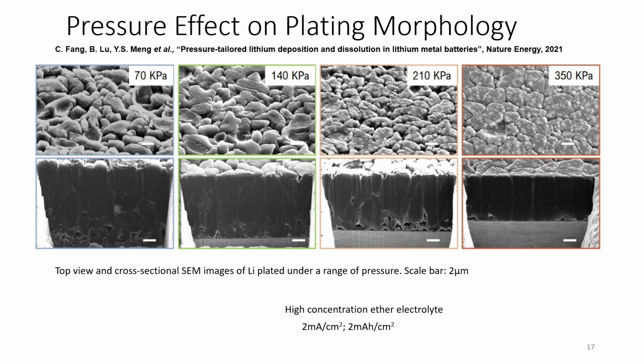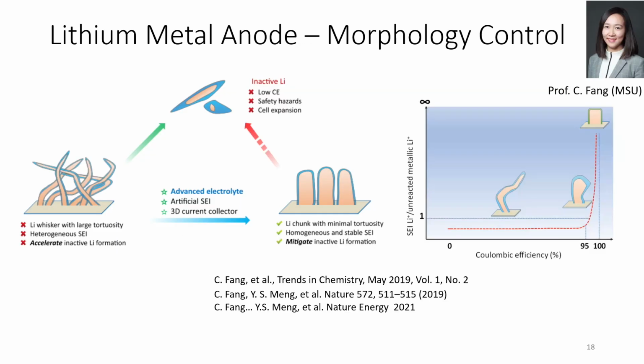Can you see that when you have almost no pressure, the lithium is highly porous, so the cross-section becomes very thick, but when you go to the optimal pressure, you can actually deposit lithium that is very dense, almost like theoretical density lithium. And this is eventually the reason why the lithium metal batteries' efficiency was improved very significantly.